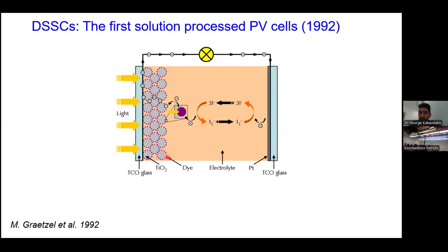Okay, and these people were very lucky, because with these titanium dioxide particles, they didn't know so far, but now today we know why this device works: these particles only accept electrons. So what was happening? Solar light was exciting the dye, then the electron was excited and transferred to titanium dioxide, then to a transparent conductive oxide, and then the electrons were extracted to the external circuit. Another electron was then injected back through a liquid electrolyte, like what is happening in a lithium-ion battery, a very similar operation. And the electron is now regenerating the dye through the electrolyte. This process can happen millions of times, and these devices are very stable and of high efficiency.